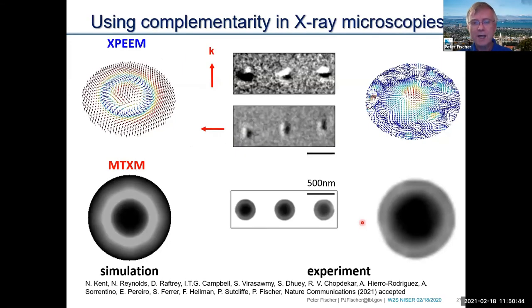This is what we found by using both a PEEM at the Advanced Light Source and a full field microscope at ALBA in Spain, the Mistral beamline. This was again the calculated, expected PEEM and MTXM images. And this is what we found experimentally. And as you can see, the agreement is astonishing. Particularly in the inner part here, there's a little focusing effect of the PEEM, which we couldn't get rid of. But it's pretty clear that this kind of spin texture we were able to resolve in full 3D.